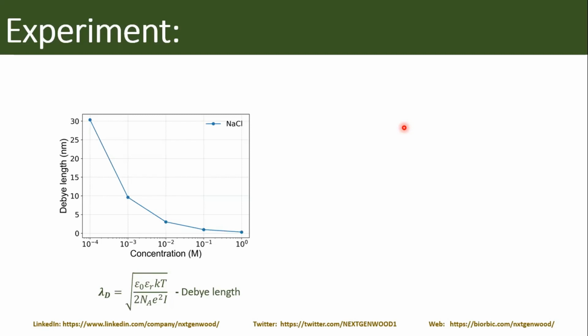So first we can calculate the Debye length, which basically characterizes the width of the electric double layer. And as you can see, if we calculate it as a function of the concentration of the electrolyte, there's a clear tendency that for higher concentrations of electrolytes, the width of the electric double layer is much smaller. And if we talk about normal capacitors and thermoelectric cells based on ions, we normally work with quite high concentrations, on the order of moles. So I call them ordinary solutions. And we can see that for this kind of system, the Debye length is close to zero, which means that in such conditions, there is no way to observe this enhancement of the thermoelectric effect due to the nano-confinement effect. And what is realistic to fabricate is something like 30, 20, 10 nanometers.